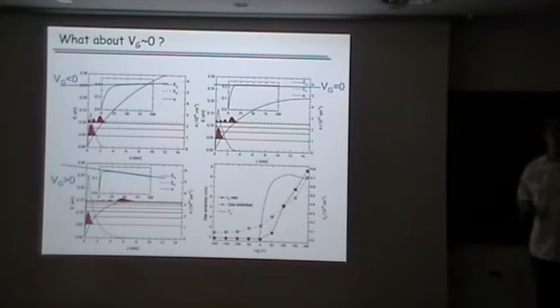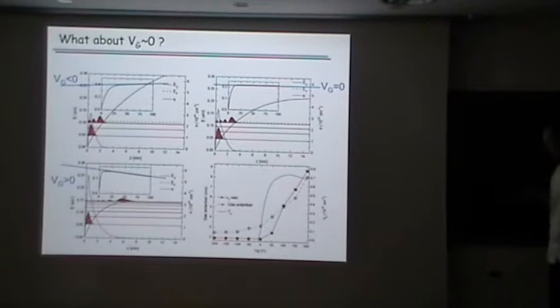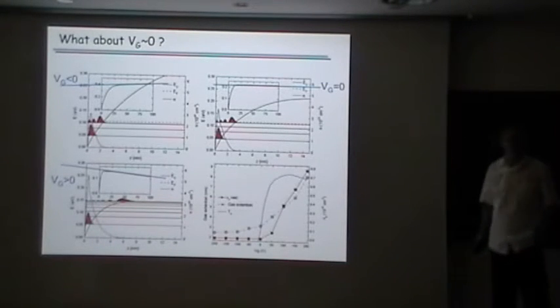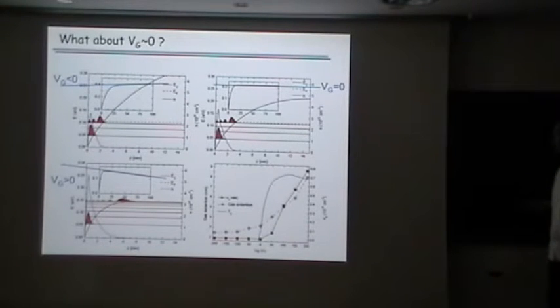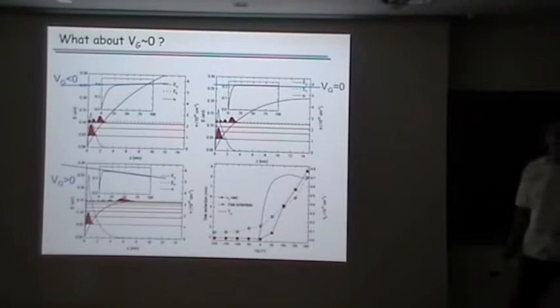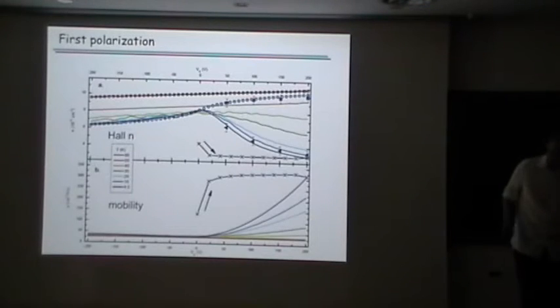Okay. Now you measure the sample and you put a gate voltage. And we have to realize something: when we put a negative voltage, of course, we bend the conduction band in this direction, and of course in the other direction when you put a positive voltage. That means that you see in the calculations the Fermi level is always very close to the conduction band.